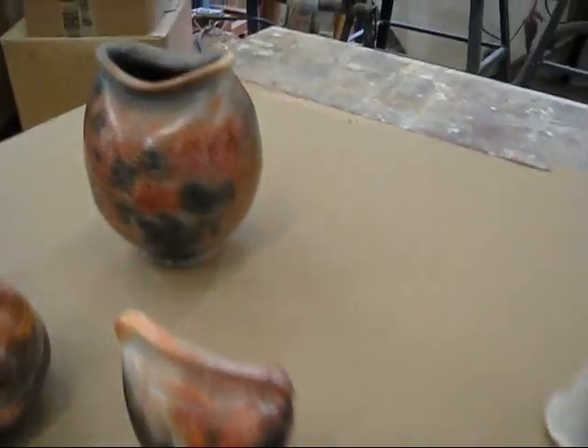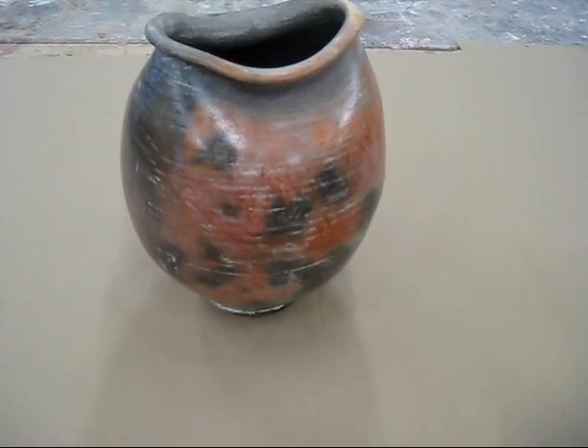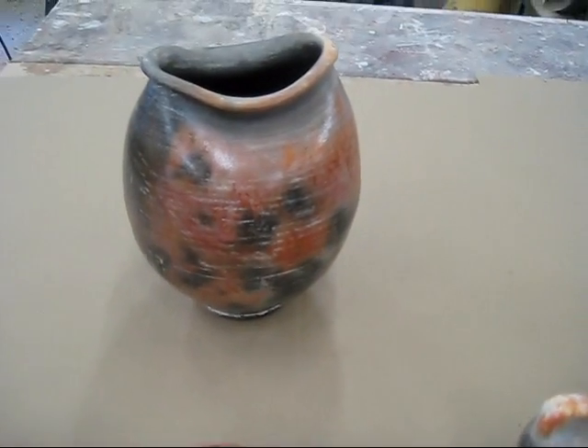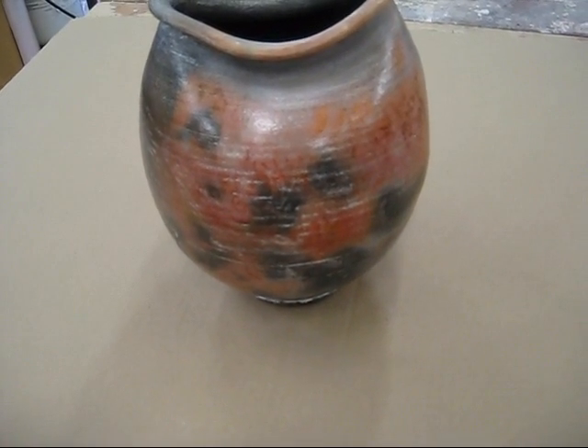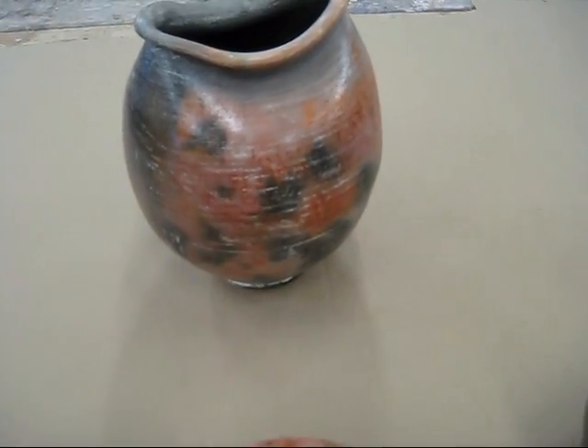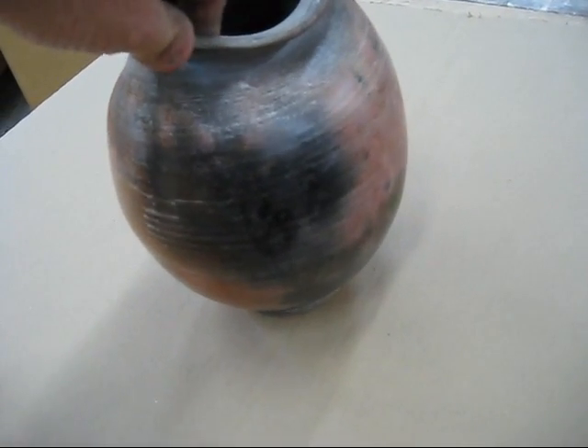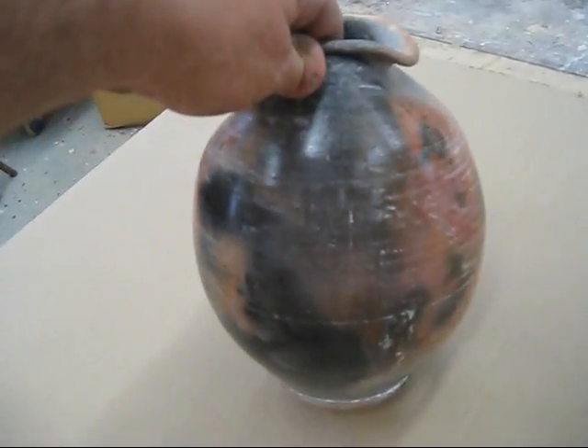This one over here is also a Raku clay piece, but I caught it nicely — it's fairly smooth with just a little bit of roughness. I did not put the slip on top of it. It was sprayed with SIG, then sprayed with ferric chloride, and then wrapped in aluminum foil. The little black spots you see are from seaweed. The darker reds in here are actually from table salt sprinkled on while the ferric chloride was still wet, just to give it some color.